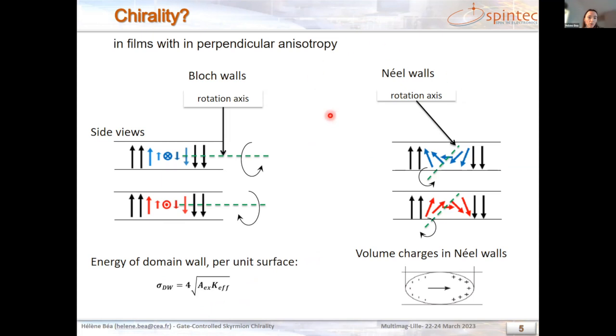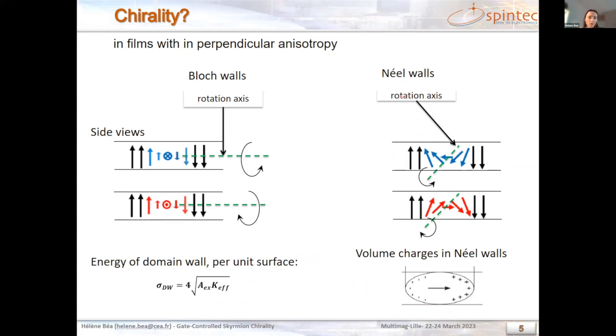You can also have Néel walls, where the rotation axis is within the domain wall. As with the Bloch case, you have two senses of rotation. In Néel walls, you have volume charges, so usually in thin films with perpendicular magnetic anisotropy those walls are not favored and you mainly have Bloch walls. When I discuss domain wall type, I will discuss between Bloch and Néel type. Chirality corresponds to the sense of rotation — clockwise or counterclockwise.